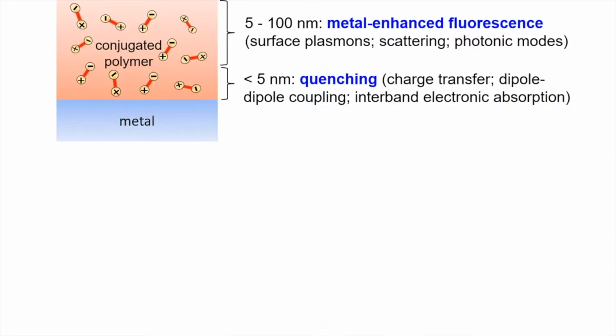In a more recent paper, we looked a little bit more closely at how metal metasurfaces, porous metal metasurfaces, can affect conjugated polymer emission. And in general, when you think of light emission from materials, semiconductors, in particular for fluorescence in this case, typically within 5 nanometers, you expect metal-induced quenching. And this is caused by either charge transfer, dipole-dipole coupling, or interband electronic absorption by the metal coupling with the excitons in the semiconductor. Further out, though, you do experience metal-enhanced fluorescence that's caused by surface plasmon resonances, scattering, or photonic modes.